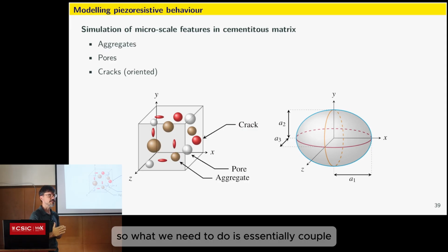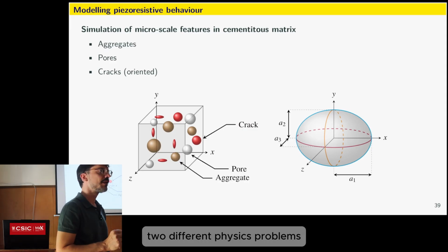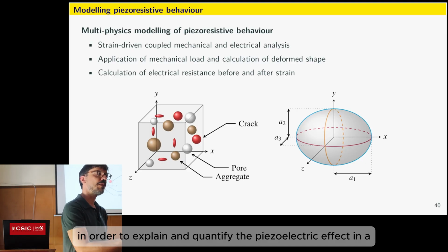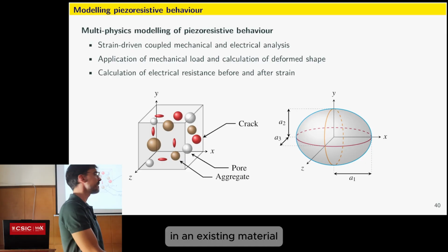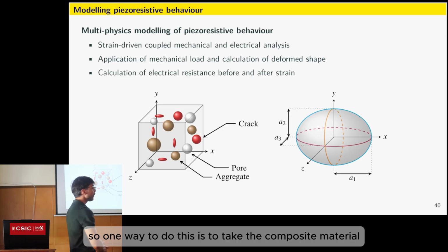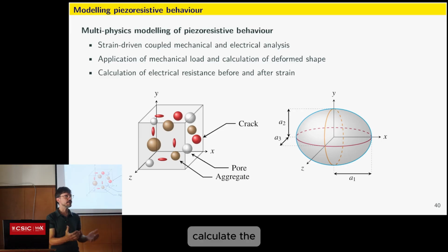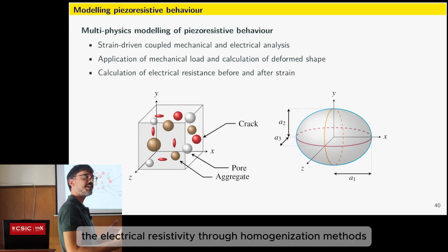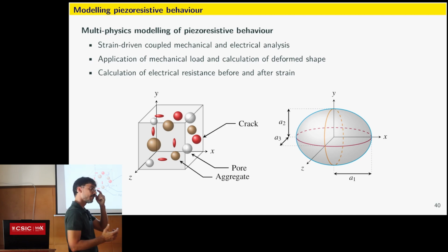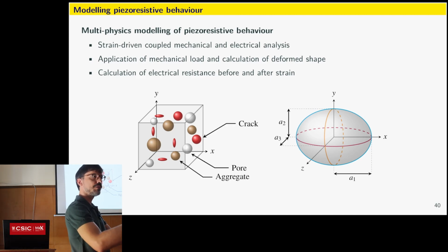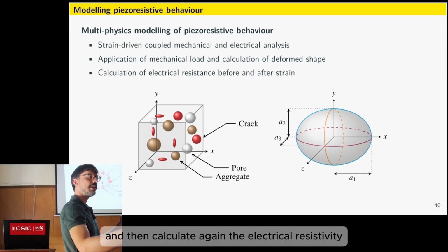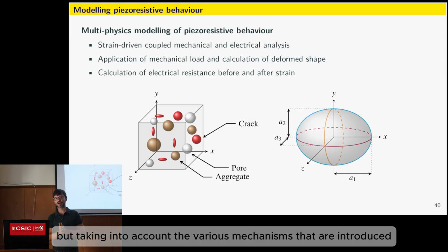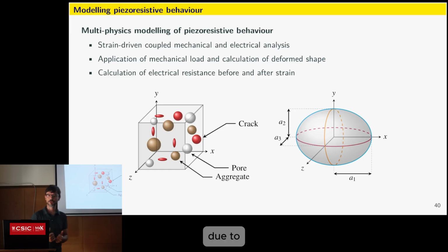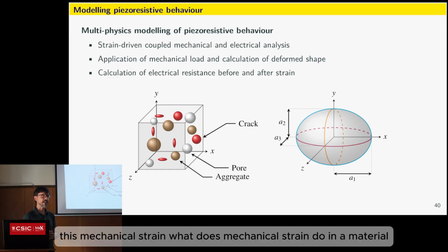So what we need to do is essentially couple two different physics problems in order to explain and quantify the piezoresistive effect in an existing material. One way to do this is to take the composite material, calculate the electrical resistivity through homogenization methods, then apply a mechanical strain, calculate how it deforms, and then calculate again the electrical resistivity, but taking into account the various mechanisms that are introduced due to this mechanical strain.